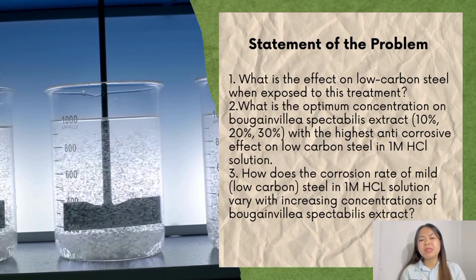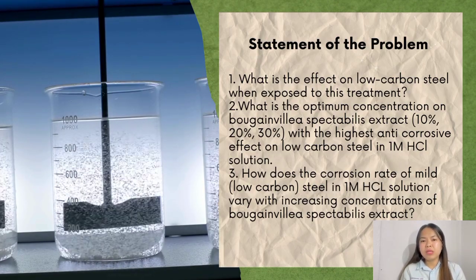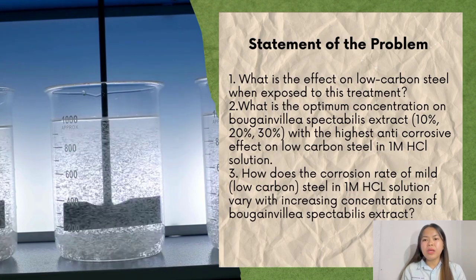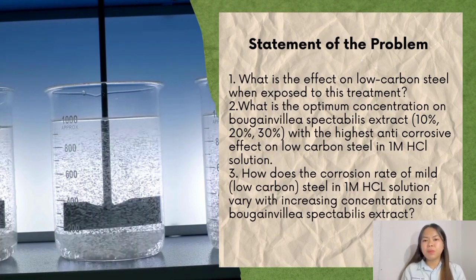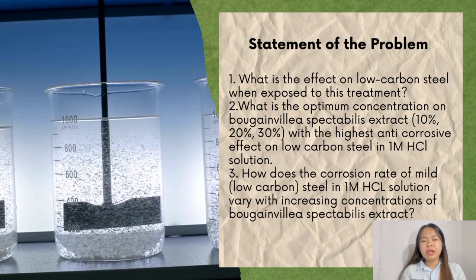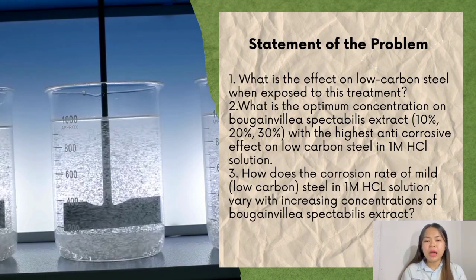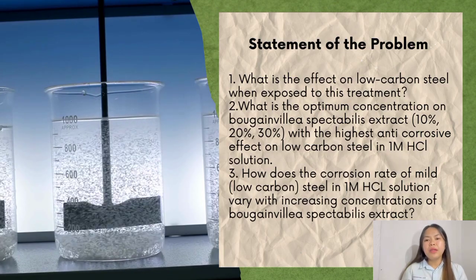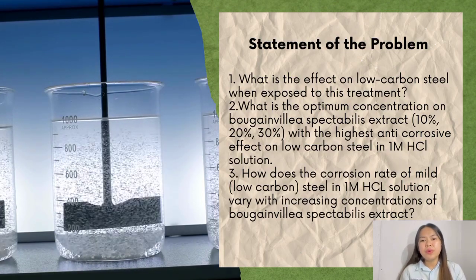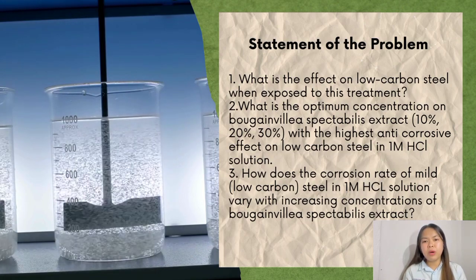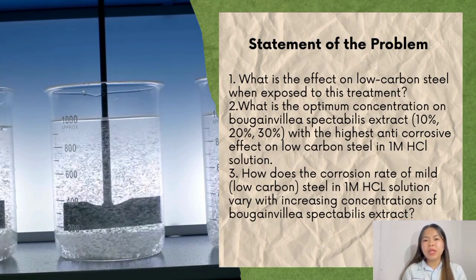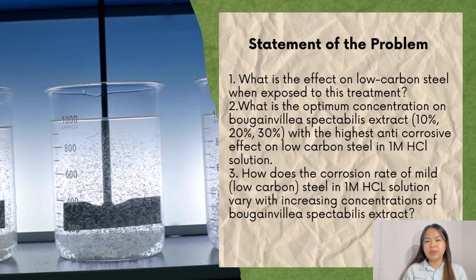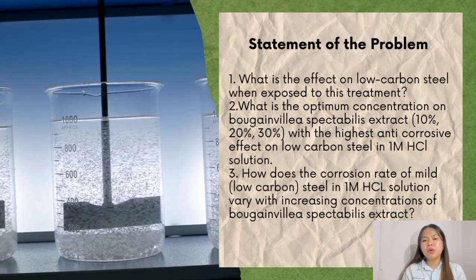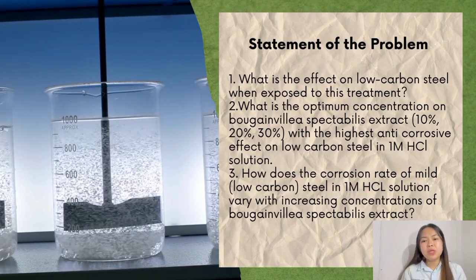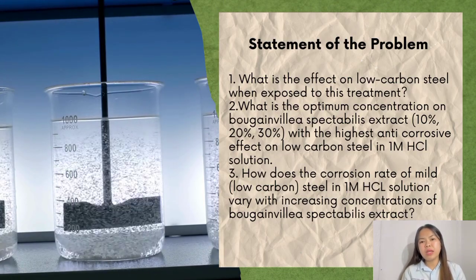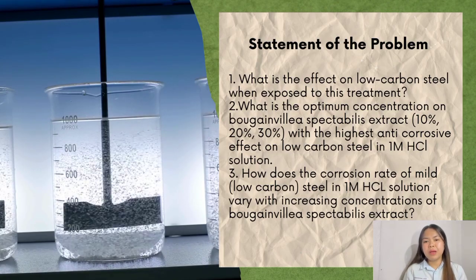So we will test the 3 different concentrations, 10%, 20%, and 30%, to identify which one offers the highest protection against corrosion when the steel is immersed in a 1 molar hydrochloric acid solution. The third question investigates how the corrosion rate of low-carbon steel in a 1 molar hydrochloric acid solution changes with increasing concentrations of Bougainvillea spectabilis extract. So this will help to understand the relationship between the extract concentration and its corrosion inhibiting properties.